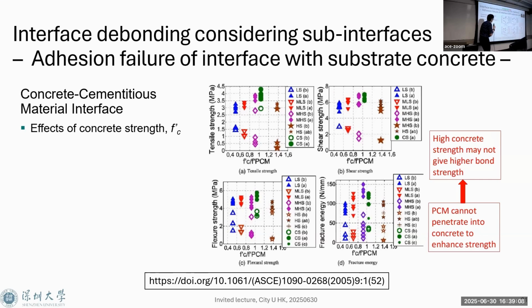Another interesting thing: if you have high strength concrete, this bonding strength becomes smaller. Because in this particular case, it is polymer cementitious mortar. Polymer is one of the mechanisms to strengthen interface strength. But polymer cannot penetrate into the concrete if it is high strength concrete. So to have better penetration, lower strength concrete is better. The lower strength concrete gives you higher bonding strength. It's something surprising. So again, strength doesn't always help.